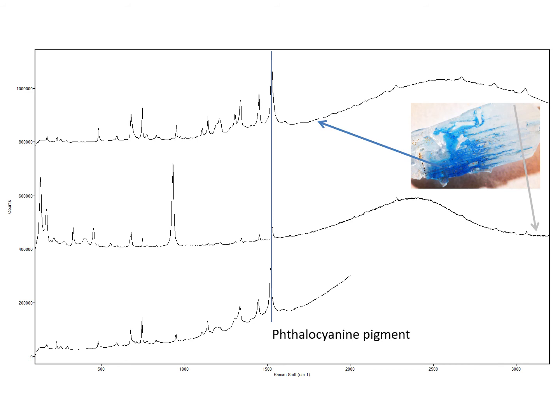determine what you have. Now, it turns out that other laboratories were looking at samples to try to identify the origin of the color, and they got peaks. They've shared the data with us. They got peaks at exactly the right portion of the spectrum for phthalocyanine. However, they were unable to determine what it was. They were going on the assumption that the coating was some sort of mineral, be it natural or synthetic, and they were comparing their spectra to databases of mineral specimens.